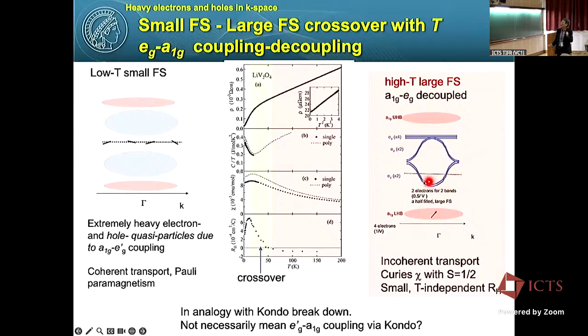And we have a big Fermi surface. At high temperature, we do see a very small Hall effect, indicating a large Fermi surface, and Curie-Weiss behavior. And transport is quite incoherent. At low temperature, they become coherent and form a small Fermi surface. A heavy semi-metal state is produced.